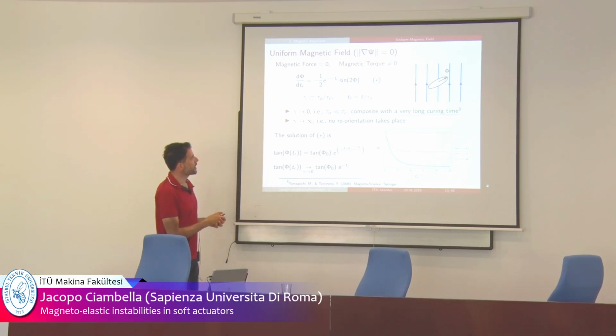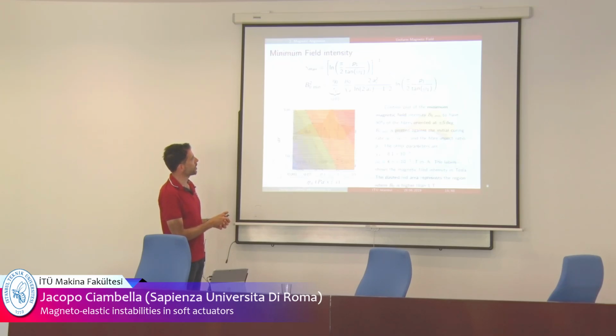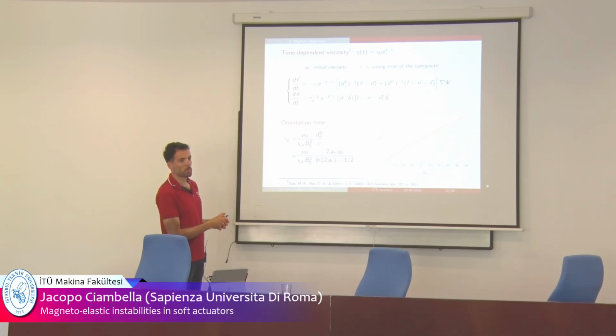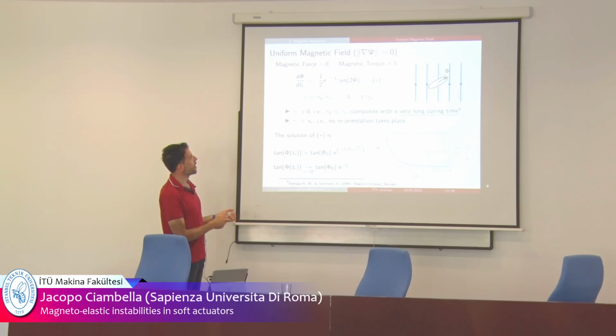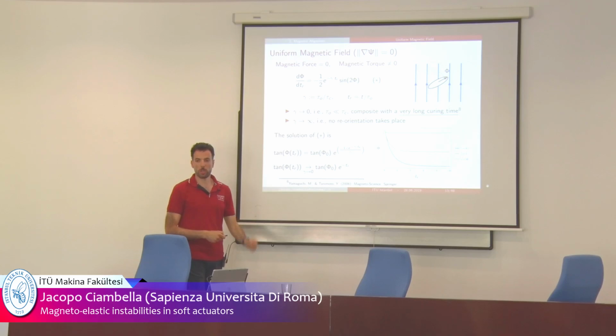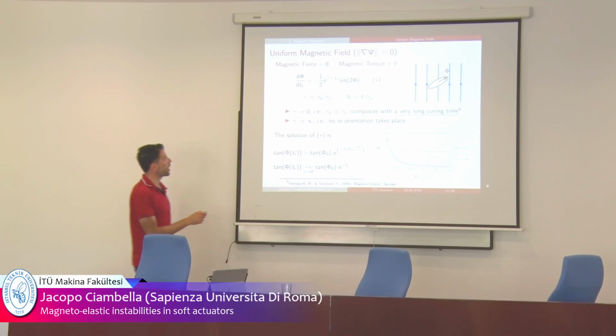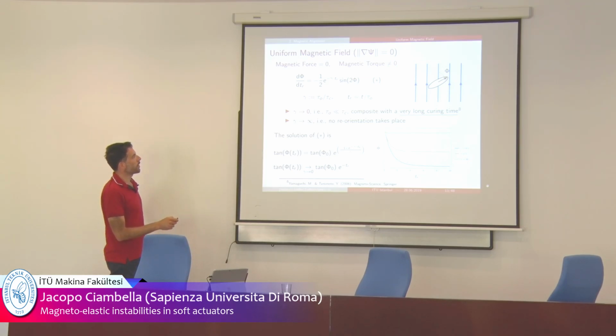Things get very easy when grad of c is 0, so you have no force. You see the first equation here cancels out. So you don't have any translational velocity, only rotational. If you restrict yourself to this problem, you only have one scalar differential equation that governs the orientation of the particles with time. Tau r is the reduced orientation time, and everything depends on gamma, which is the ratio between the curing time of the composite, how much time it needs to be cured, and the orientation time of the particle.